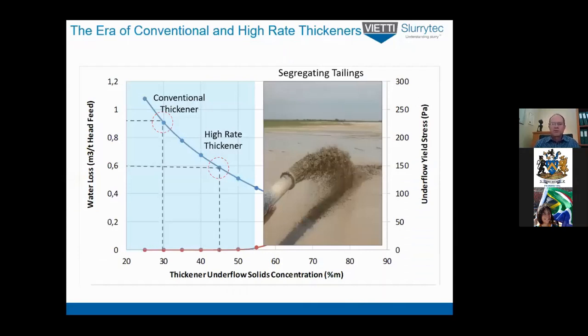So this is a graph quite nicely describing the performance of a dewatering unit in terms of water loss, cubic meters per ton of head feed. So obviously, as you dewater, you become more efficient, you thicken the underflow more, you recycle the water better, so you use less top-up water. So your water loss curve starts dropping down, becomes more efficient. And at the same time, your underflow solids concentration gets thicker. And a nice way of describing the thickness of the underflow is the sheared yield stress of that material. So this is a curve particularly for diamond tailings, because I've got a lot of information on it, so it makes sense to me to do it on diamonds.